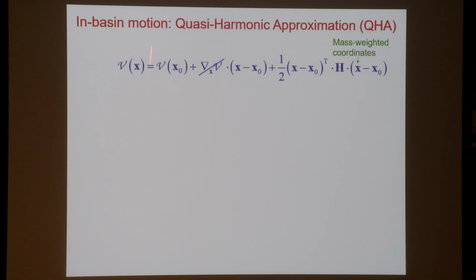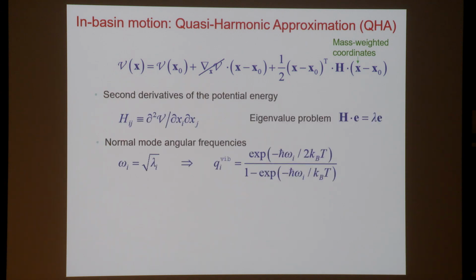That is, we will expand the potential energy in powers of the mass-weighted coordinates. The first term is 0 because we're working at a minimum. This Hessian matrix of the second derivatives with respect to the mass-weighted coordinates plays a very significant role because its eigenvalues can give us the normal modes of vibrational motion around the minimum. So the square roots of the eigenvalues at the minimum give us the normal mode frequencies. And from each normal mode frequency, we can calculate a corresponding vibrational partition function.